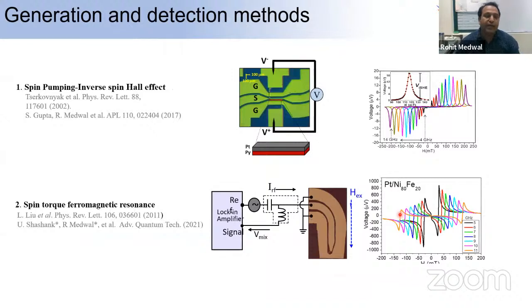I will show how we can use the spin Hall effect and inverse spin Hall effect in the device geometries we are working on. There are two different schemes: spin pumping with inverse spin Hall effect, where we make the magnetization precess about the applied magnetic field, which gives rise to a polarized spin current. We can convert this spin current back into charge current using the inverse spin Hall effect. That is the first technique. Second, we have also used spin torque ferromagnetic resonance, where we convert charge current into spin current. Please make a note of these two techniques. Technique one, the spin pumping inverse spin Hall effect measurement, is for spin to charge conversion, whereas technique two, the spin torque ferromagnetic resonance, is for charge to spin conversion.